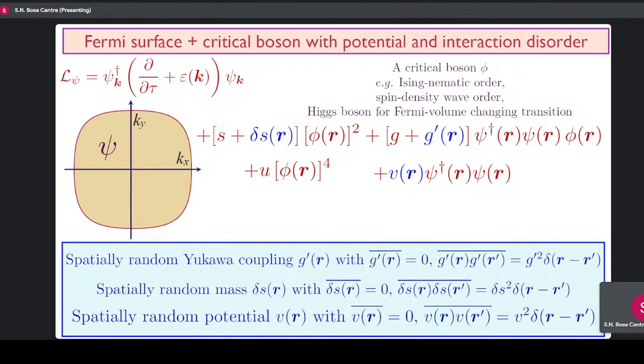So first thing you realize is that there's something in this model that wasn't there in the other model, which is this random mass term. We said, well, we don't like this random mass term because it's causing a lot of trouble. And if you just look at it, it's extremely relevant. And if you do some kind of mean field theory, you get rather strange looking results.